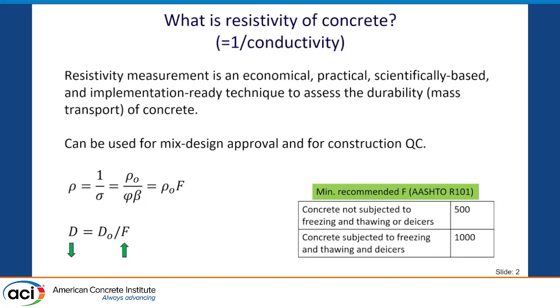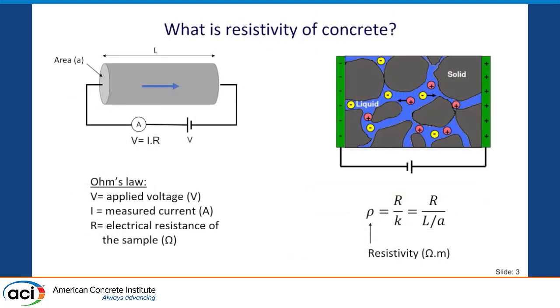Because of this, for example, in AASHTO R101, the performance engineering mixtures spec, there are minimum limits for formation factor. You have to be at least 500, or you have to be at least 1,000, depending on exposure conditions. In terms of measurements, it's very simple.